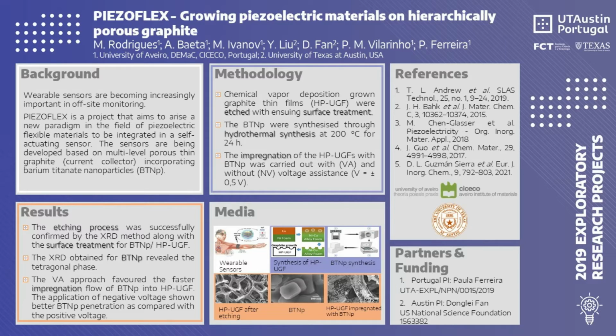The foam impregnation was then carried out by droplets, and this process was tested with and without the assistance of voltage that is thought to accelerate and facilitate the impregnation flow. The voltage-assisted impregnation was fulfilled with both positive and negative voltage, using a positive electrode at the top and a negative at the bottom of the foam, and vice versa.